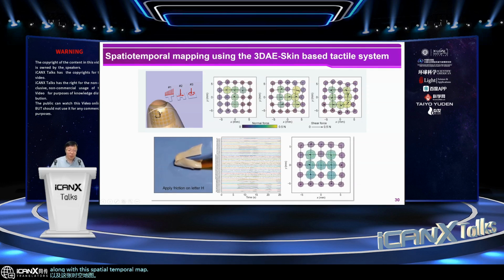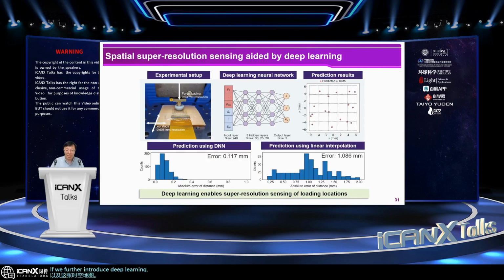Okay, if we further introduce deep learning neural network model, the precision of force sensing, in particular, the loading position, can be improved significantly, which is also called super resolution sensing. This is because the DNN model can establish the implicit mapping between the magnitude and location of the applied force and the relative resistance changes of the 240 sensors. And through learning of this network, the precision of the prediction can be improved significantly.